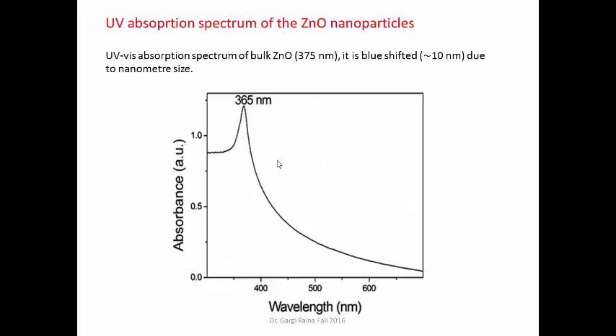This here is the UV-Vis absorption spectrum for zinc oxide nanoparticles. Generally, if you look at the UV-Vis absorption spectrum of bulk zinc oxide, then you get a maximum absorption peak at 375 nanometer. But here we see that the peak is shifted by around 10 nanometers due to the nanometric size of these zinc oxide nanoparticles. So from these changes in the absorption peak positions from the UV-Vis spectra, you can determine the change in the property of the material from bulk to nanometer.